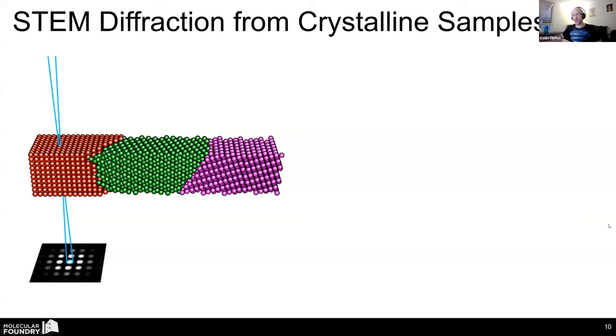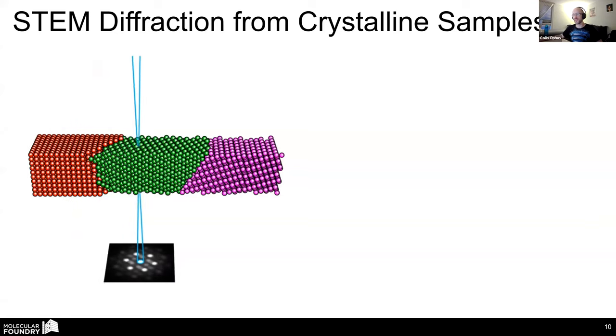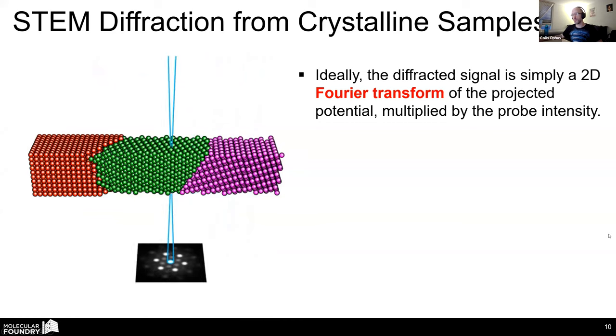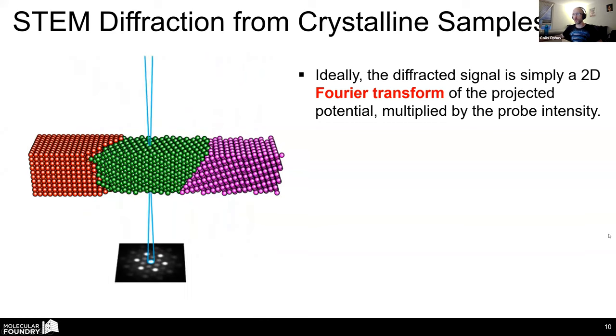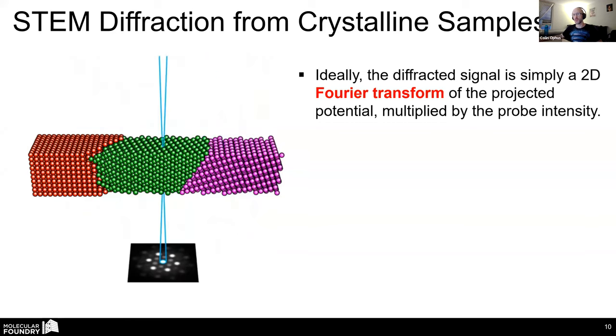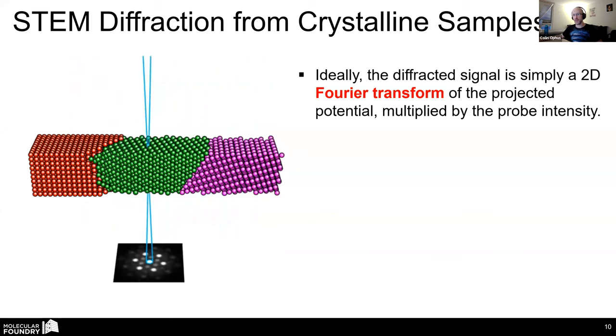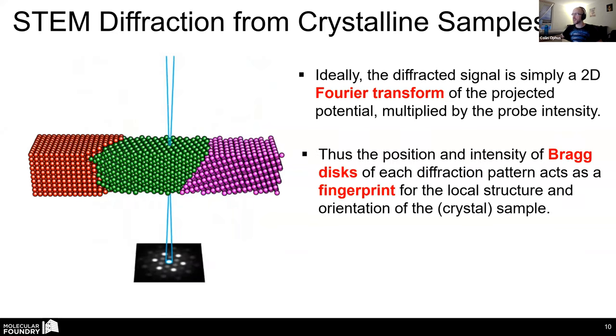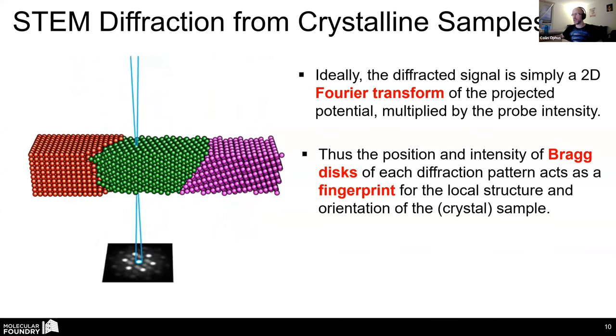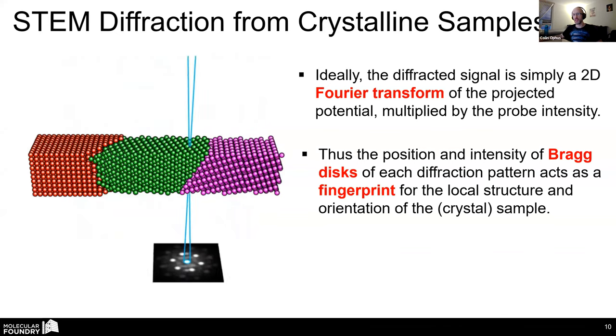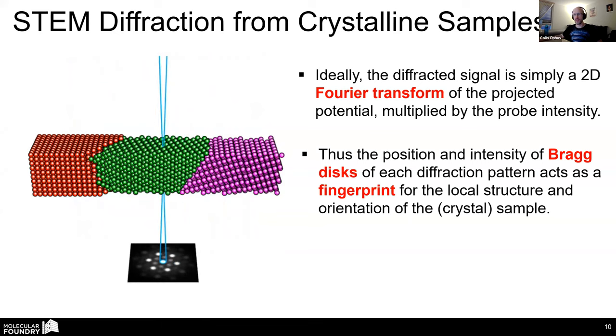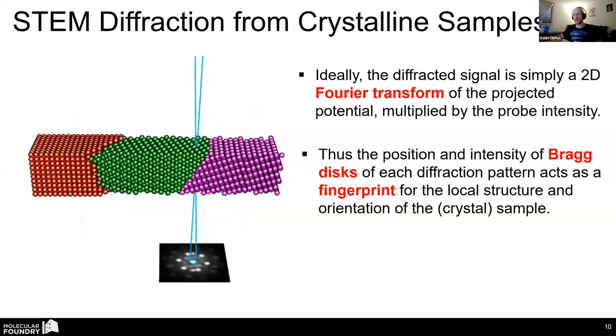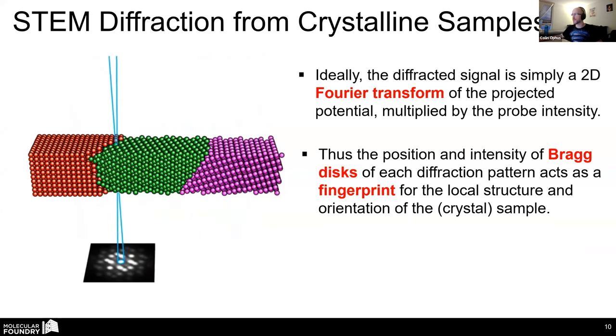Okay, so I mentioned a quick crash course in what exactly these signals contain. This is a toy model showing a converged electron probe diffracting through 3 crystalline grains. What we're essentially measuring is a selected area diffraction pattern, but the area is the intensity distribution of the probe on the sample surface. So we're essentially measuring a convolution, multiplying the probe intensity by the sample potential. And then in the far field, it's in Fourier space or reciprocal space, so we get a diffraction pattern here.